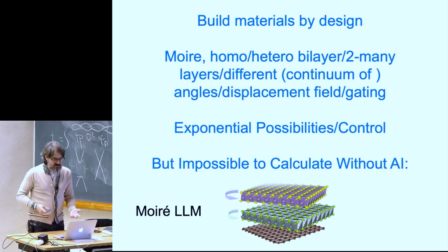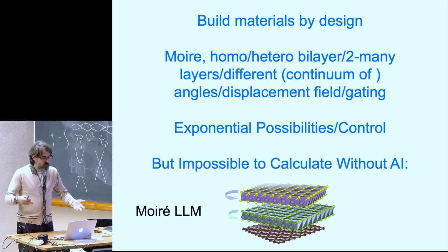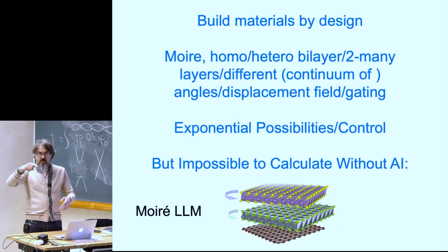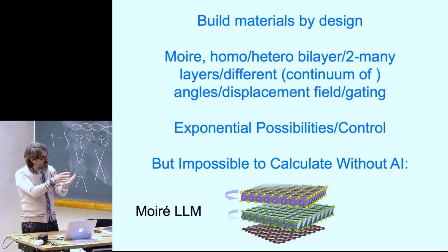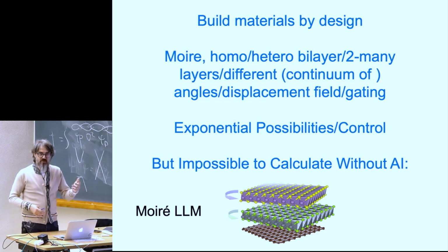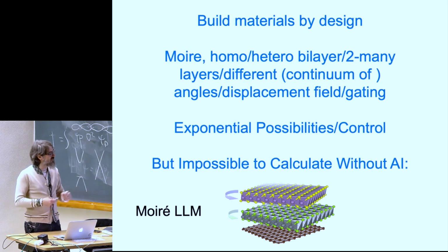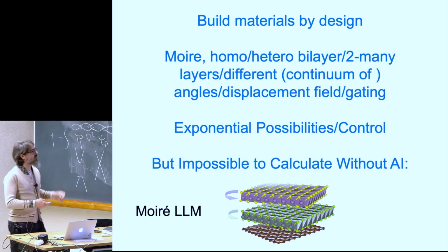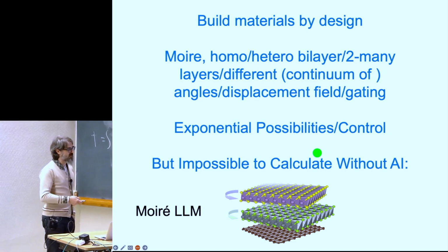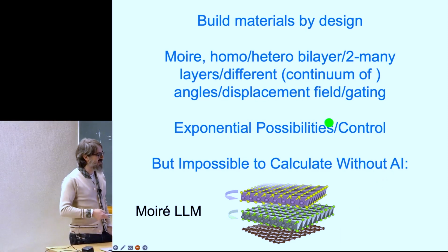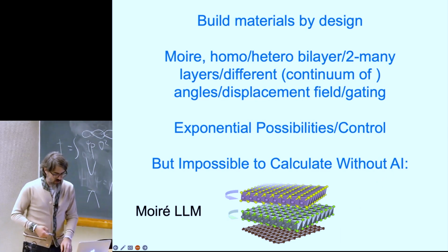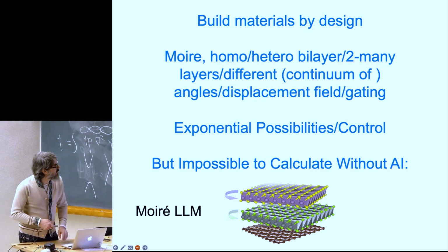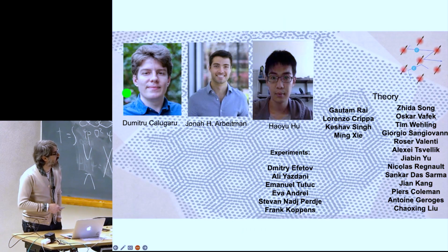Okay, so then you can ask, well, what are we going to do? We want the phase diagram of such a system, but the angle is continuous, for example. So one of those calculations where I showed you that the band structure becomes flat, going from large angle to small angle, takes about 6 months to do correctly because you have relaxation. So you obviously cannot do 6 months for each and every one of these infinite possibilities. Now this is obviously just pulling this out of the pocket, but hopefully AI can help with calculating this, because otherwise we cannot.